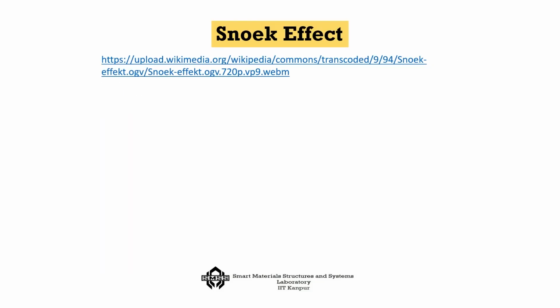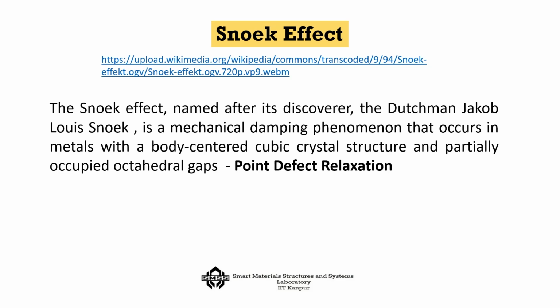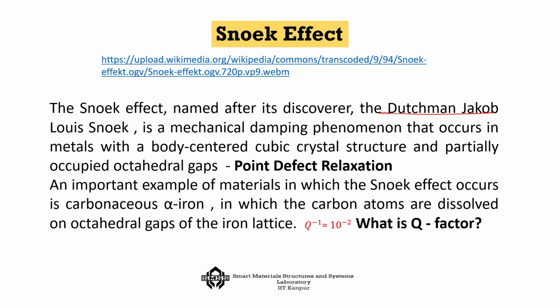Now, let us look into the damping. What are the possible ways in which the structure can dissipate energy? One of them is called the Snoek effect. It is named after its discoverer, a Dutchman, Jacob Louis Snoek. It is a mechanical damping phenomenon that occurs in metals with a BCC cubic crystal structure and partially occupied octahedral gaps, and this is a point defect relaxation. This happens, for example, in carbonaceous alpha iron systems, in which the carbon atoms are dissolved in the octahedral gaps of the iron lattice, and there you see damping happening because of the relaxation of the point defects in the crystal. This is what is known as the Snoek effect.